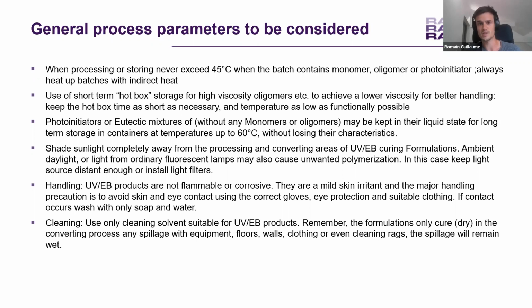We have to be careful to shade sunlight completely away from the processing and converting areas of the UV or electron beam curing formulations. The ambient daylight, or also light coming from ordinary fluorescent lamps you can have in the area, may also cause unwanted polymerization of your formulation. So in this case, we must keep the light source distant enough or install light filters to avoid that kind of issue. About the handling, UV or electron beam products are not flammable or corrosive.